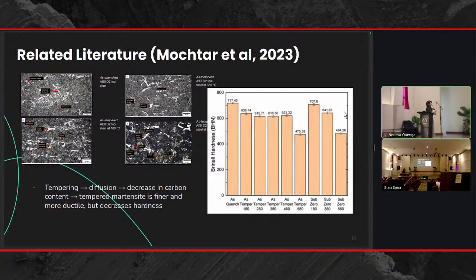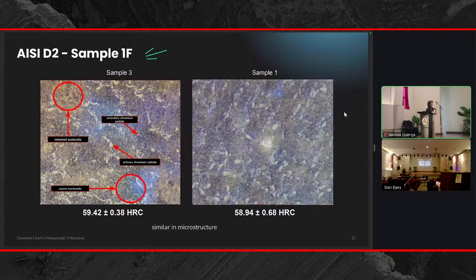So tempering reheats that structure and increases the diffusion of carbon, thereby decreasing its hardness in exchange for finer and more ductile tempered martensite. So this was consistent with our findings.